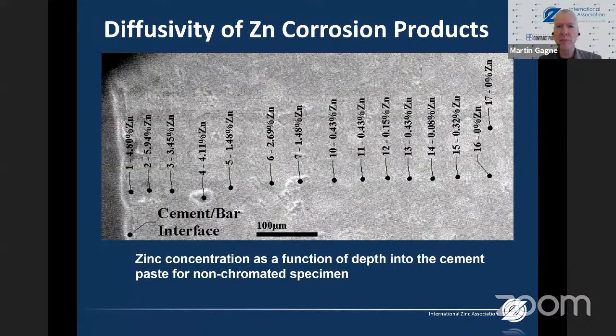I talked about the corrosion products on zinc. Here we've done some analysis. We can see the cement reinforcing bar interface on the left-hand side, and we measure the concentration of zinc as we move away from that interface. So we can see in the cement paste, there's quite high levels of zinc, almost to 1 millimeter away from the bar. So rather than build up at the interface, the zinc corrosion products dissolve into the pore solution in the concrete and migrate away from the bar, so the stress doesn't build up and we don't have the same potential for cracking and spalling as we do on the plain black steel.